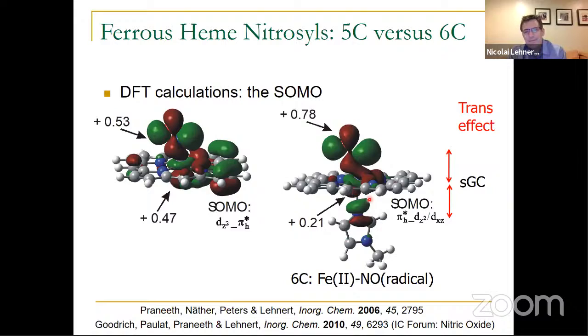On top of this, you can see that in this orbital, the interaction between dz square and the sigma donor orbital of our imidazole ligand, which we use instead of histidine in the model complex, is actually anti-bonding. This orbital is of course empty without NO, and when NO binds, this orbital becomes singly occupied, and it is anti-bonding with respect to the iron imidazole bond. And that is a direct reflection of this trans effect. So the binding of NO weakens the iron imidazole bond because we're occupying an orbital that is iron imidazole anti-bonding in nature.